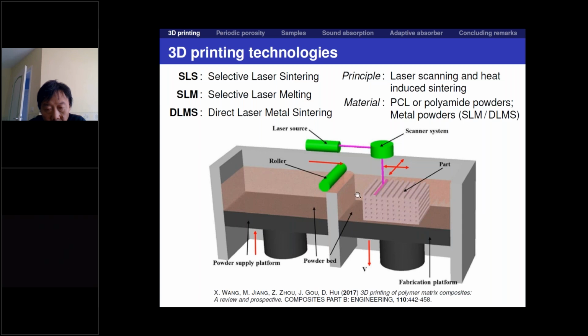So it moves down only by this small distance, and the roller sweeps the powder, the first layer of the powder, onto the fabrication platform. Then we use the laser beam to 3D print the first layer. The platform goes down by the thickness of the layer. This one goes up, and the whole process is repeated.